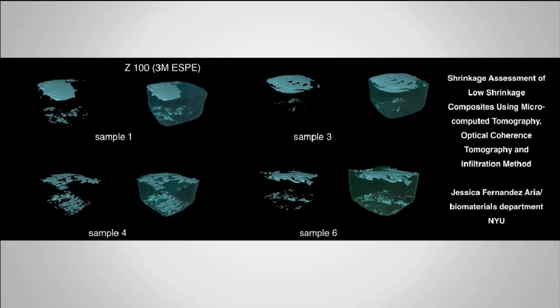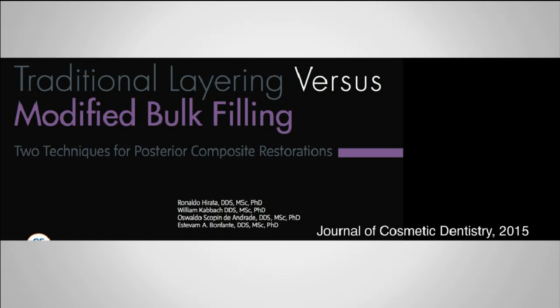And if you compare this with a regular composite, for instance, this is a composite from 3M, a regular one, not a bulk fill one, the shrinkage of a regular composite is going to come on the occlusal surface and also at the interface, especially at the bottom of the cavity. And this is something that we have to avoid. So these images just show us the idea of these bulk fill materials that you can apply up to 4 millimeters. You have the polymerization up to 4 millimeters, and you keep the interface sealed.